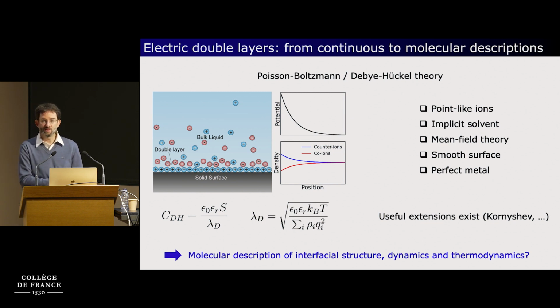From this theory, you can also predict the capacitance of the interface, which is given here. And the capacitance depends again on the permittivity of the solvent, and it's inversely proportional to this Debye screening length, which typically for a 0.1 mole per liter solution of monovalent ions in water at ambient temperature is about 1 nanometer. Now, there have been many theoretical developments to improve this canonical description, in particular to account for correlations between ions, and in particular due to their finite size. You can look, for example, at various works, including that of Alexei Kornyshev, but there are other approaches to deal with that problem. And what I would like to discuss today are the contributions, or some contributions, of these classical molecular dynamics simulations to understand the interfacial structure, dynamics, and thermodynamics.